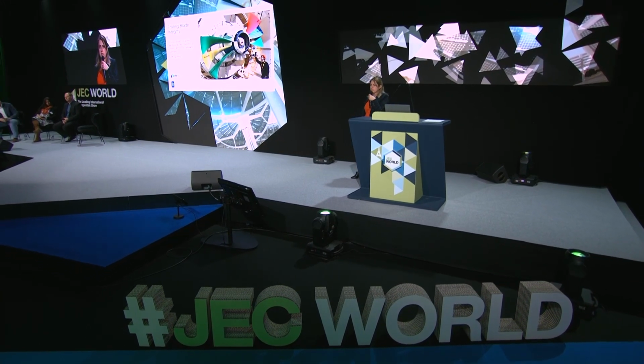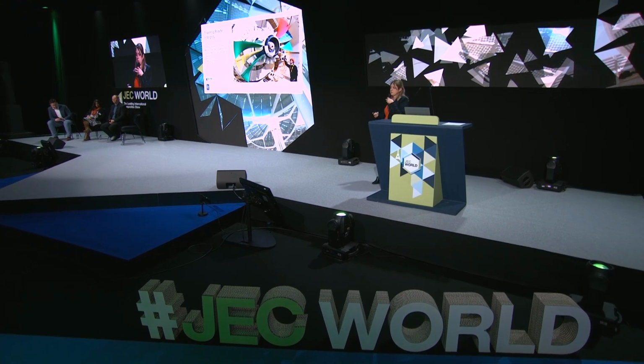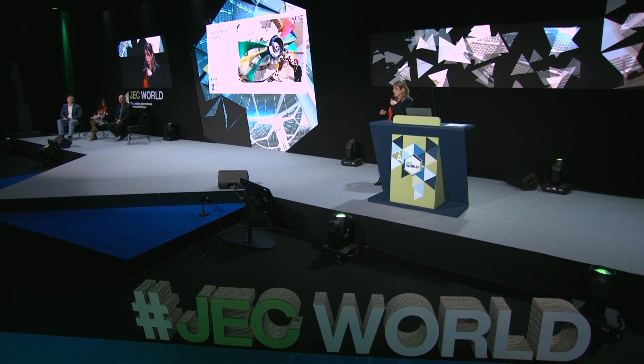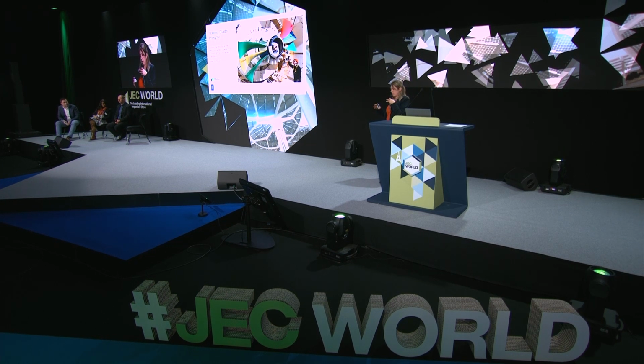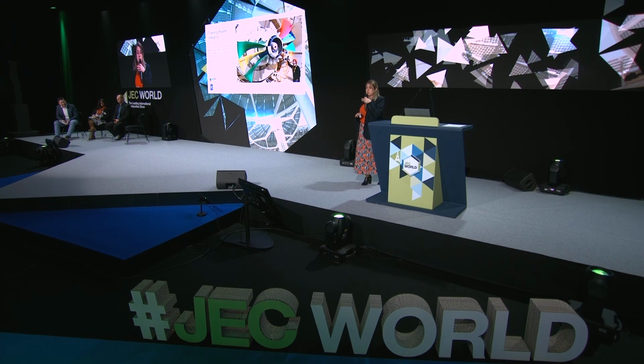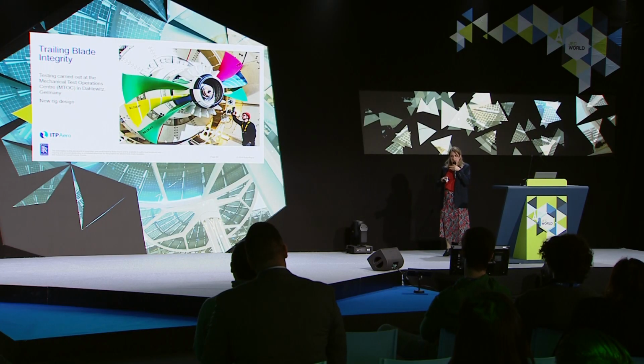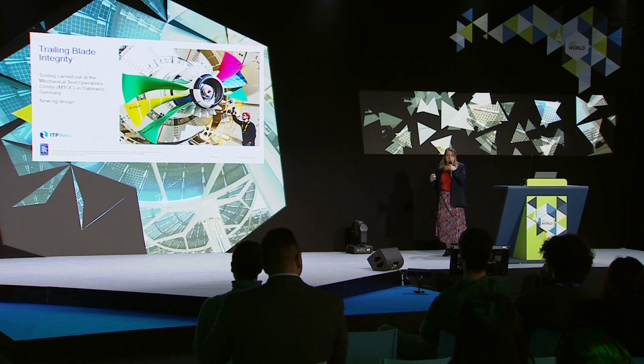The image here was actually taken during the commissioning phase, so the trailing blade isn't fitted. We then also have in there between the blades, the annulus line is filled with a set of composite annulus fillers. These are all attached to a rather large UltraFan titanium fan disc. And the white stubby blades that you see in there are actually rather heavy lumps of steel that were fitted to ensure the stressing on the disc was correct.